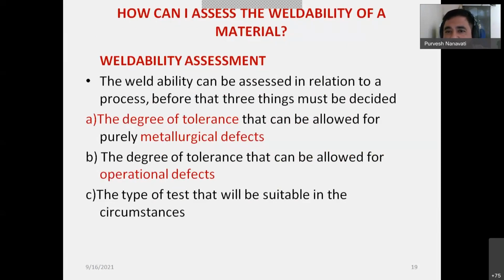Before we go for the weldability assessment, we should keep in mind the degree of tolerance that can be allowed for purely metallurgical defects. I'm sure in the previous lectures you have understood about some defects produced due to metallurgical causes. Some are operational defects, right? Metallurgical defects like inclusions, and process related ones like porosity, cracks, slag inclusion, oxide inclusion. The operational defects are like gas pockets, cracks or fissures. These are the process related defects. So first we have to be sure about the degree of tolerance, whether we will allow these defects and to what extent.